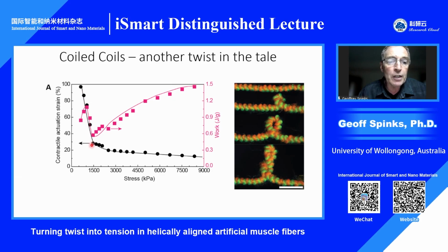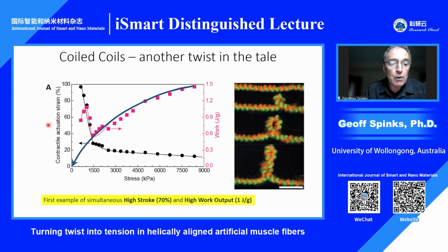Now it drops off fairly quickly because supercoiling is quite sensitive to the applied stress. But the other interesting factor is if we look at the work done, in the highest case, it's well over 1 joule per gram. And normally we see the work done decrease monotonically to 0 as we decrease the applied stress. And we certainly see that over a large range, but then there's this region here where it shows a different trend, where the work done actually increases with further decreases in stress. And this is in the supercoiling region. So in fact, we're able to demonstrate for the first time simultaneously a high stroke and a high work output, which in every other system doesn't appear.